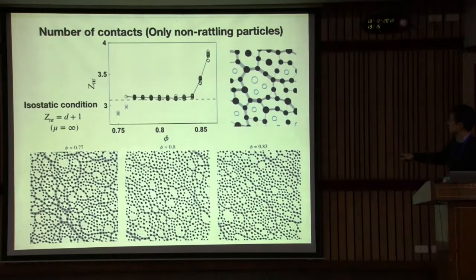Then I observed this plateau. This is close to isostatic condition 3. Initial condition is totally relaxed, so no contact, coordination number zero. Under strain, under flow, in dying flow under constant stress, they develop neighbors. And stuck when the value is close to 3, but actually 3.1. Interestingly, this different volume fraction, coordination number is roughly same.